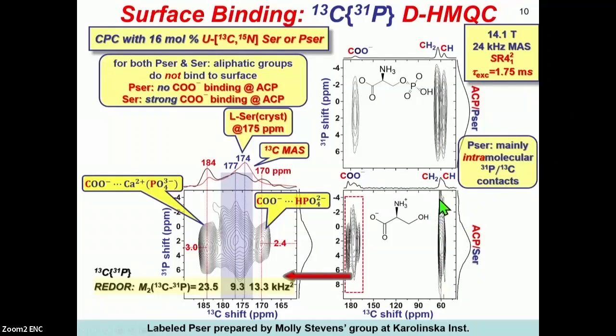and we know from carbon-phosphorus REDOR experiments as well as MD simulations that there are no aliphatic groups that bind to the surface for either serine or phosphoserine. The same thing goes for the carboxy group of phosphoserine. So in the correlation spectrum here, the peak intensities merely reflect the intramolecular contacts with the organic phosphate group.